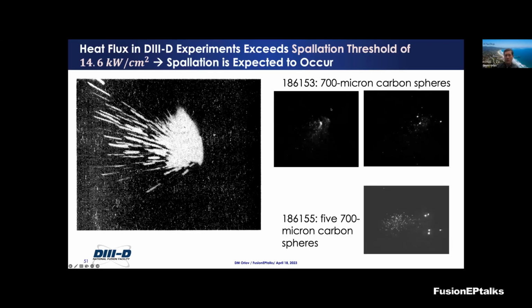Here are a few images from a few discharges with those glassy carbon spheres, and you could see a lot of spallation, a lot of shards flying around, similar to what was observed in the materials that were tested for the Galileo descent probe.